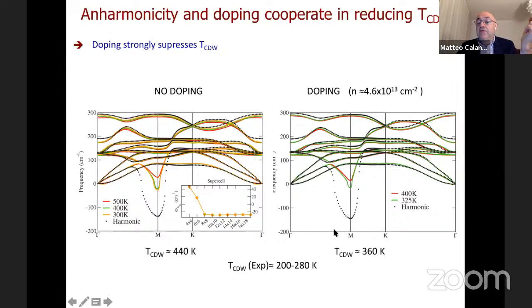And indeed, if you consider this doping, the temperature is lower, approximately 360. That is now a more favorable comparison with the 200 to 280 Kelvin that you have in experiment. Of course, experiments have different degrees of doping, and it's difficult to evaluate. Also, the ARPES have different quality, but this means that we are in the ballpark anyway, and there is a combined effect of anharmonicity and doping.